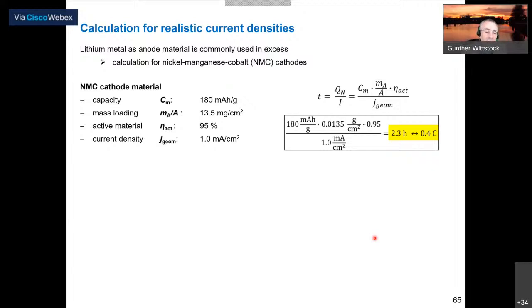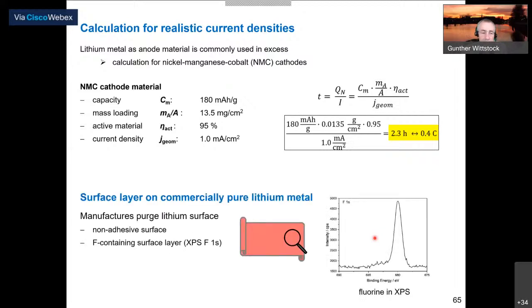So first, we calculated what would be a realistic current density for such a lithium metal electrode if it would be operated against an NMC cathode. That is shown here. We know that the surface of these lithium metal electrodes is treated by the manufacturer with a layer which makes them non-adhesive. This contains fluorine, as one can see from XPS.